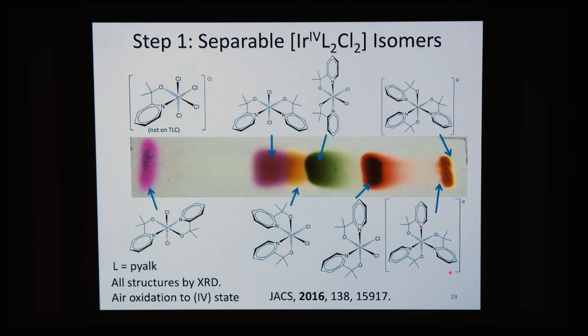And their energies by DFT differ by a very, very big amount, but they interconvert very, very slowly. The iridium 6 water 3 plus complex has a half-life of 300 years for water exchange. So iridium is the most inert of all coordination inert ions. And so this helps us by allowing us to separate things without the geometries being affected.